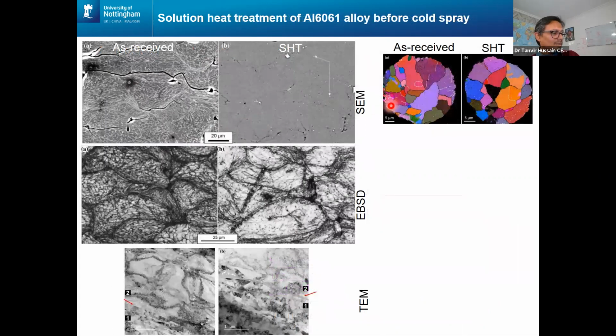Moving on to a little bit of the mechanism. So here we are working with 6000 series alloys, and that's my Euler image of the as received powder and the solution heat treated powder. Low angle grain boundaries are white lines, high angle grain boundaries are black lines. You can see there's a fair bit of low angle grain boundaries in the as received condition. So the conventional wisdom used to be gas atomized powders are dislocation free, not stressed.